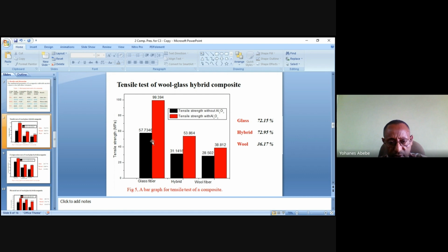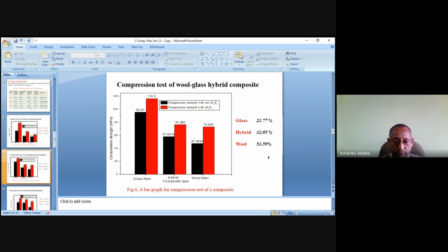So the difference you can observe, in terms of percentage, is that the glass fiber composite has 72.15% improvement, and that of the wool fiber is 36.17%, whereas the hybrid is 72.95%. The same holds true if we are looking at the compression test of the wool glass hybrid composite.